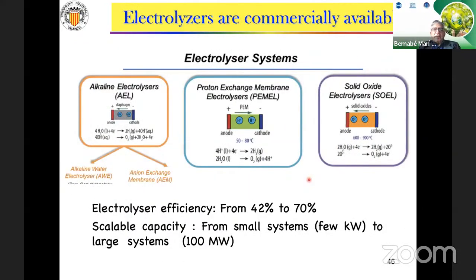Right now the electrolyzers are commercially available. You can purchase alkaline electrolyzers, proton exchange membrane electrolyzers or solid oxide electrolyzers. They are available in the market. The efficiency changes depending on the technology used, ranging from 42% to 70%. What is very interesting is that the capacity is very scalable. You can purchase a small system with a power of a few kilowatts, or a large system on the order of 100 megawatts. So these electrolyzers are in the market, and you can purchase the capacity you want.